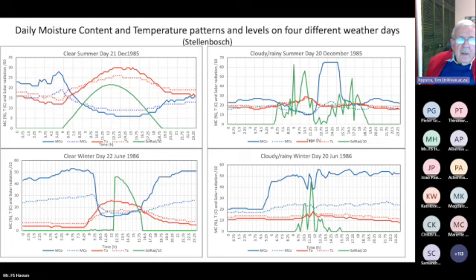Then at the same time, when the sun is not shining, in other words in the early mornings, you will find that the outside temperature is lower than the inside, or the temperature on the roof. That is what we call undercooling. With undercooling, you have the same phenomenon as water droplets precipitating on a glass, say a cold beer. So you will have undercooling leading to precipitation on the material, causing a rise in the moisture content shown in the solid blue line there. Not as smooth, but it's happening because of turbulence and so on.